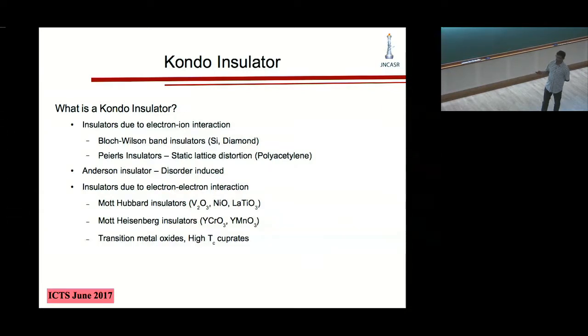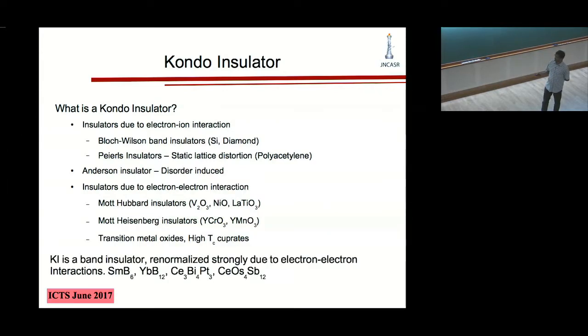Then there could be a Peierls insulator, for example, with a static lattice distortion. Then an Anderson insulator, which is disorder induced. And then there could be electron-electron interaction induced insulators, for example, Mott-Hubbard insulators, of which examples are here, Mott-Heisenberg insulators, transition metal oxides, high Tc cuprates. So among these, the Kondo insulators have not appeared. But actually, Kondo insulators are nothing but the same band insulators, but in a different avatar.